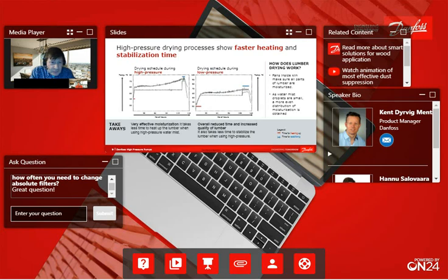Then we are coming to this blue area, which is called stabilization, where you are basically cooling down the lumber inside the kiln, and it's vital that you always follow the humidity level, so that the outside surface of the wood is wetter than inside the wood. Otherwise you are cracking the wood. And when you are able to do this much faster, it saves time and the quality is much better.